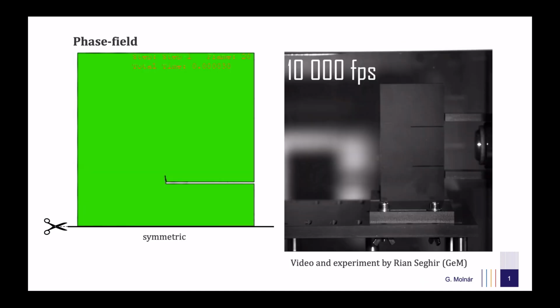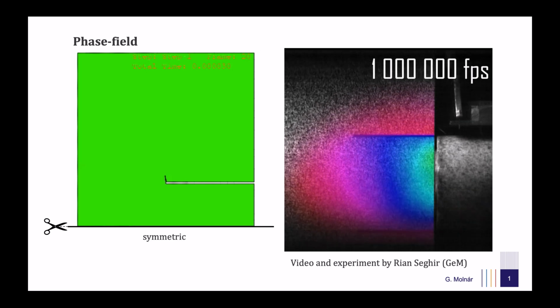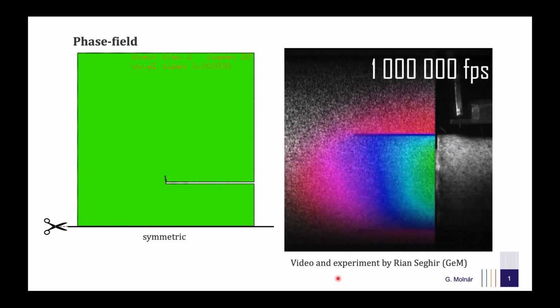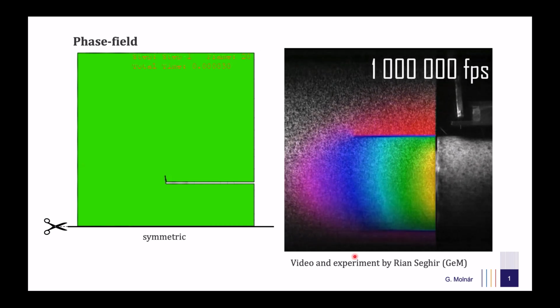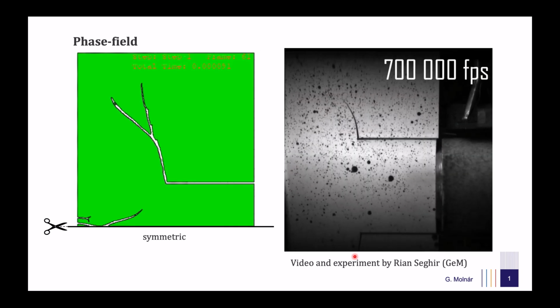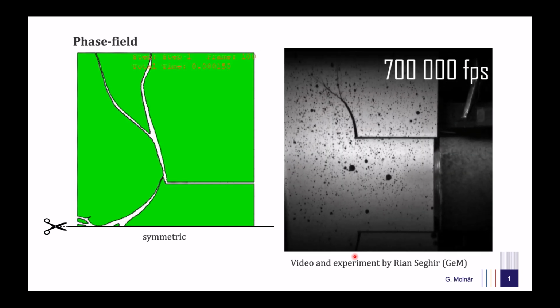To start, I will present a relatively complex example, both experimentally and through simulations. This experiment was conducted by my friend Rian Seghir in Nantes during my postdoc years. Here, a projectile approaches from the left and impacts a polymer specimen. As the elastic wave reaches the pre-notch, a new crack initiates at a well-defined angle. The crack then accelerates and branches at a specific point. Interestingly, these features remain consistent across experiments, revealing key fracture characteristics.